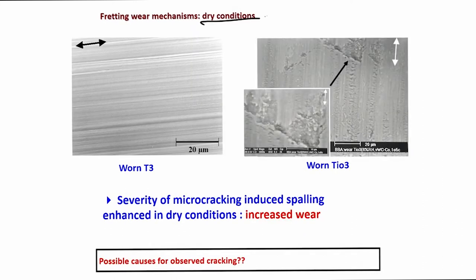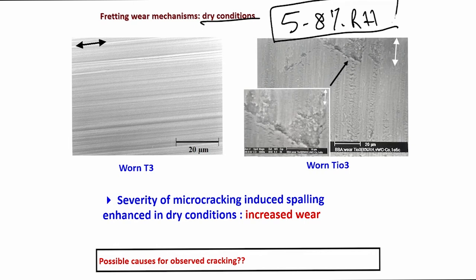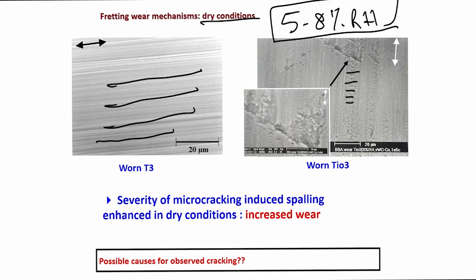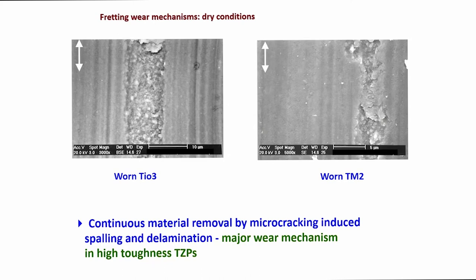Now, let us look at some other observations. What happens in the dry conditions? You remember that we have also done the test at the 5 to 8% relative humidity conditions. Here the severity of the abrasive scratches increases, and that corroborates well with the wear volume of this material. But what is more interesting to see is that even this micro cracking, which is perpendicular to the fretting directions, also increased in severity. And in some of the cases, we have found a very clear signature of spalling. So, this spalling is increased in very dry conditions, and that leads to increased wear of these materials.